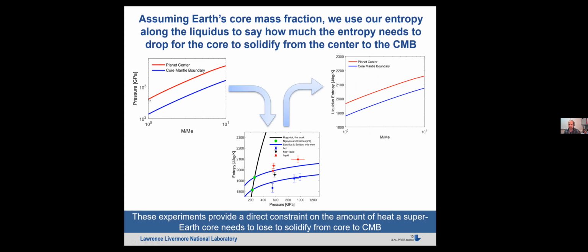So we did some interior structure calculations to obtain the pressure at the center of the planet and the pressure at the core mantle boundary. This is now pressure in log space versus planet mass from 1 to 10 Earth masses, sort of the super Earth regime. For these pressures at the planet center and the core mantle boundary, we then relate those to the entropy along the liquidus, so that we can say how much entropy you need to lose to go from solidifying at the planet center to solidifying at the core mantle boundary.